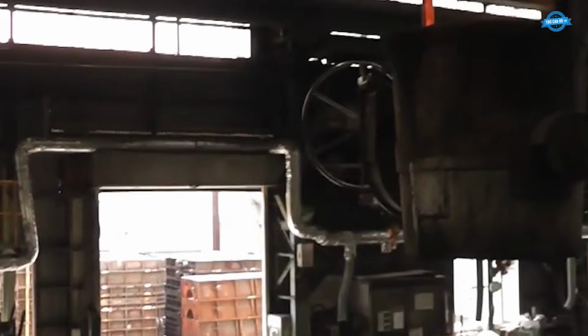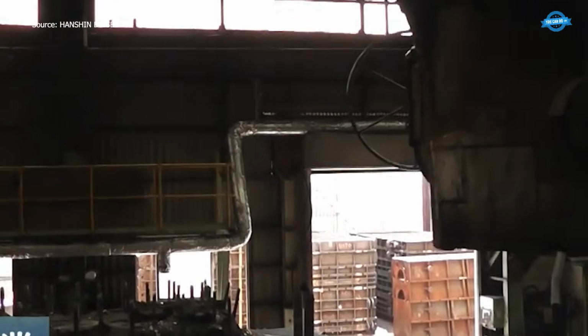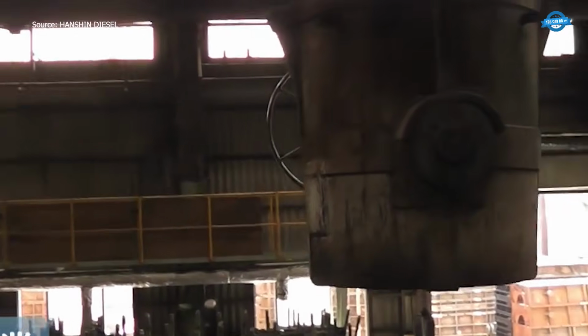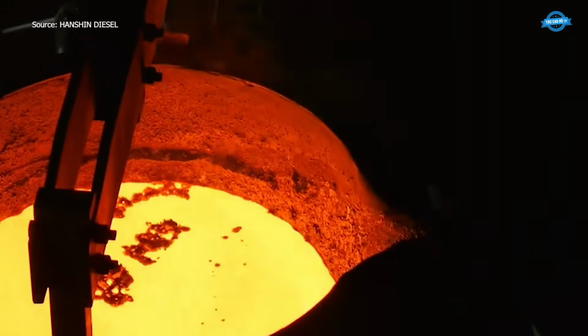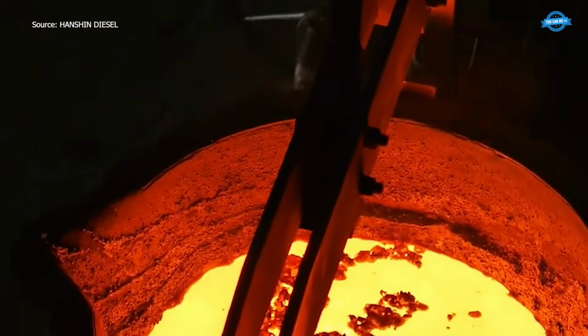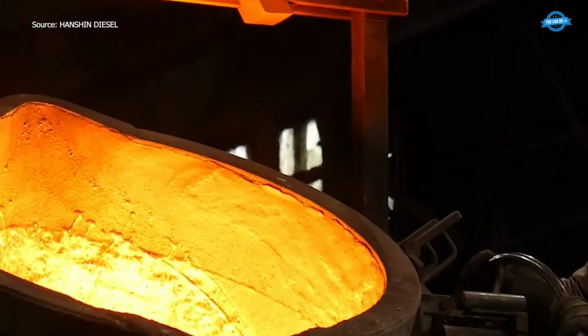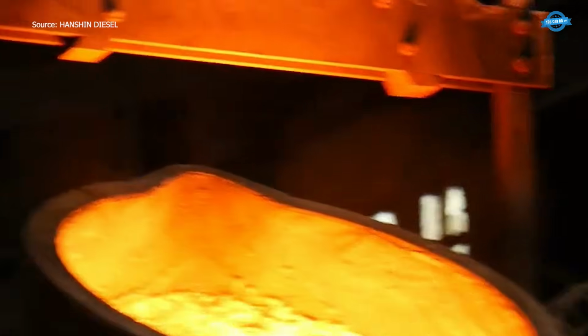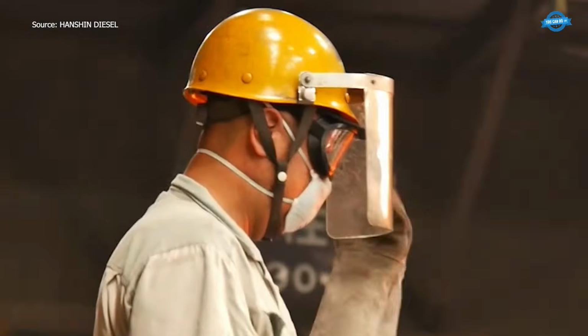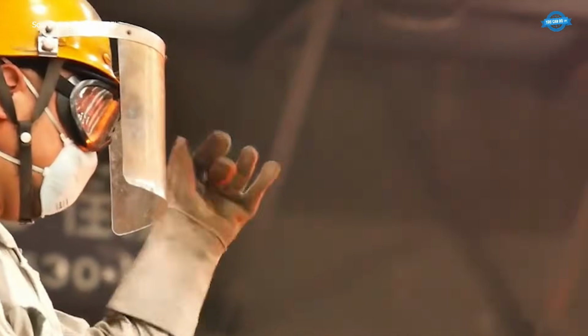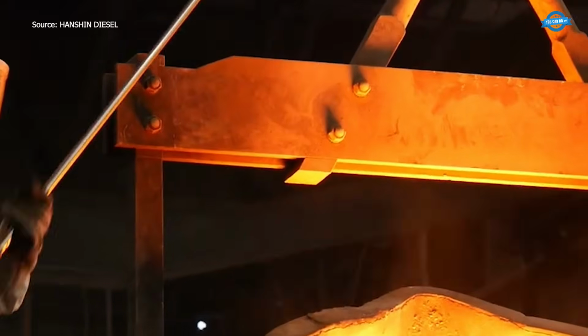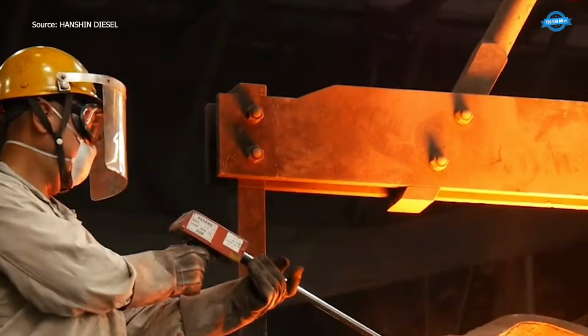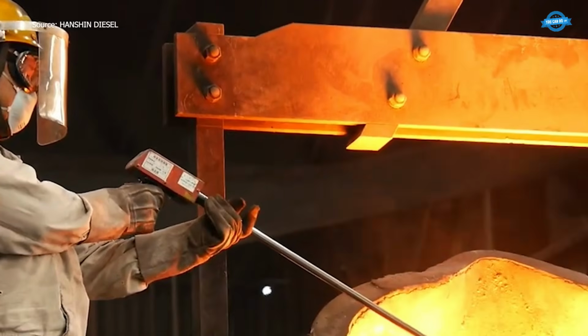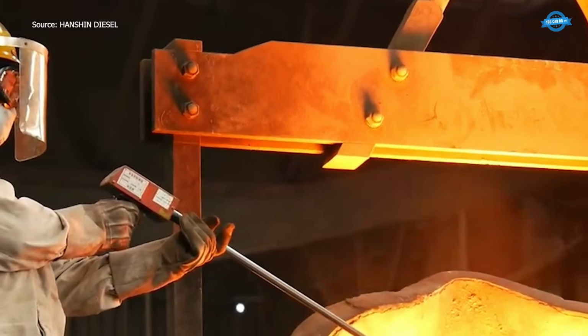The workflow prepares for pouring as molten iron is drawn from the furnace at 1,460 degrees Celsius, with a single ladle carrying 4 tons of metal. That heat isn't just about melting, it defines fluid behavior before contact with the mold. That kind of thermal control feels like holding raw power on a tight leash. The metal is guided forward without delay, keeping consistency intact before the next phase.